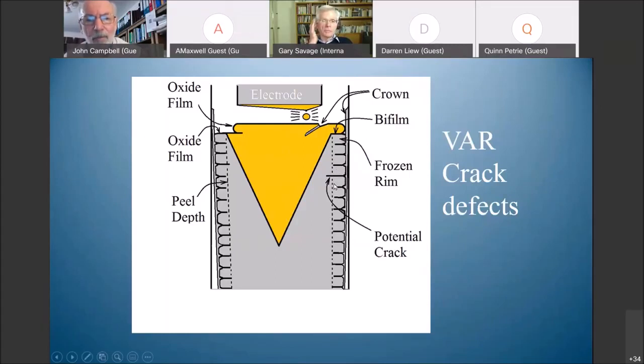Now, these cracks are known about. In fact, if you were to take this ingot and try to forge it, it just cracks. It cracks straight through. And that's despite the fact that this would be, say, a nickel-based alloy, which can't crack because it's ductile. Okay, if you have a crack in it and you try to extend the crack, it won't extend, it just blunts. But here we have a nickel-based alloy, say, in which when we go to forge it, it cracks right through. And just the ingot will often fall into pieces. I mean, this is not a trivial failure.